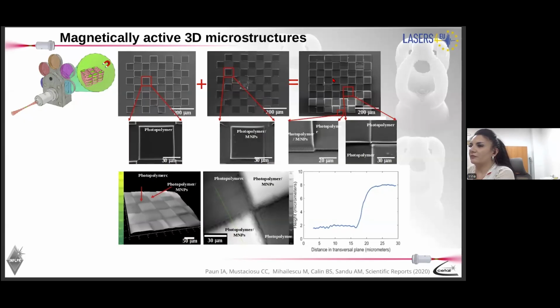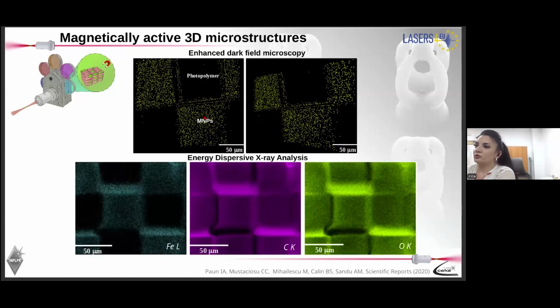These are SEM micrographs of our structures, magnetic and non-magnetic. Together, they make the chessboard-like structure. And we wanted, of course, to check if we have these magnetic nanoparticles inside the structures at the position where we want them to be. We did this by enhanced dark field microscopy, and then we checked for the presence of iron. We did this validation by EDAX.